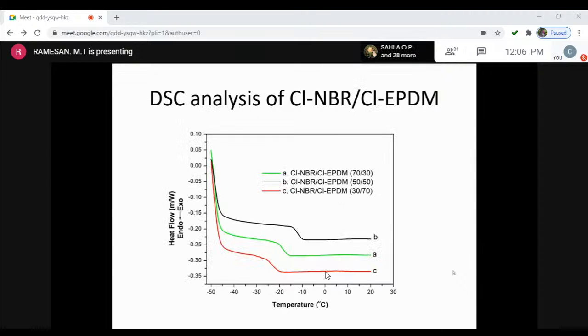And this is a differential scanning calorimetry study, measuring the glass transition temperature. Glass transition temperature means the temperature at which the polymer, the rubber, becomes hard. It can be easily broken at the glass transition temperature. And here you can see that a single glass transition temperature is obtained. This is a clear indication of a miscible polymeric system.